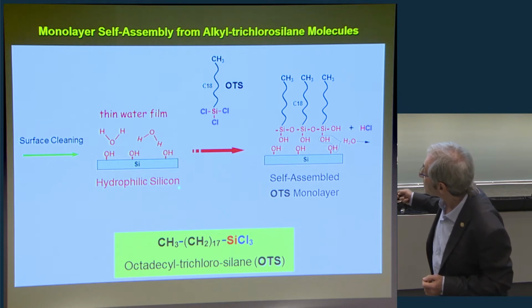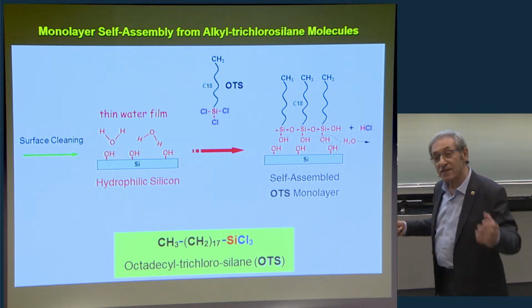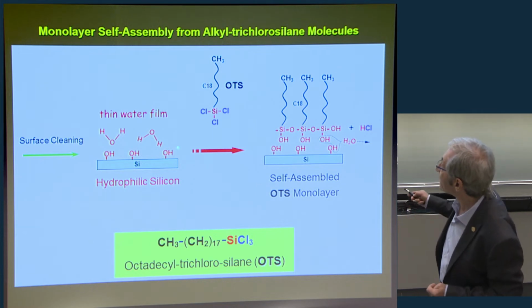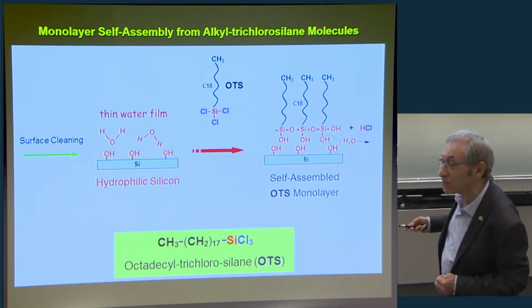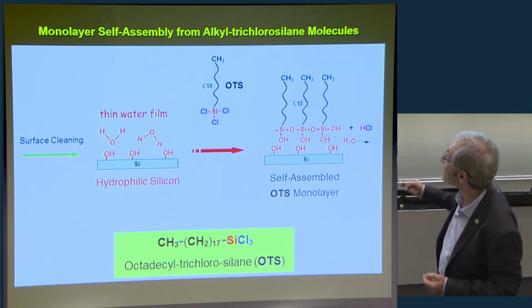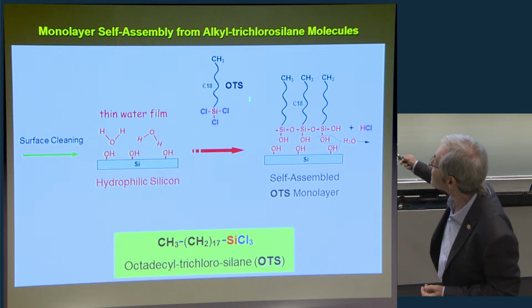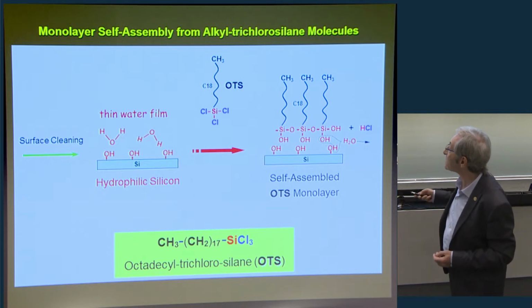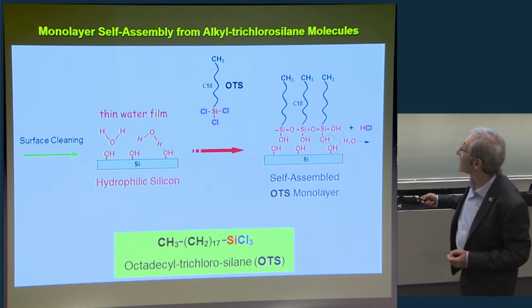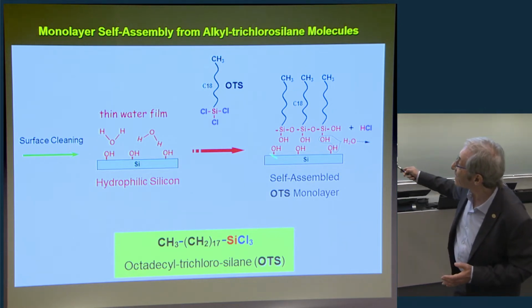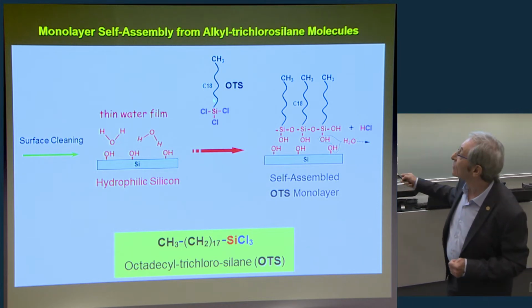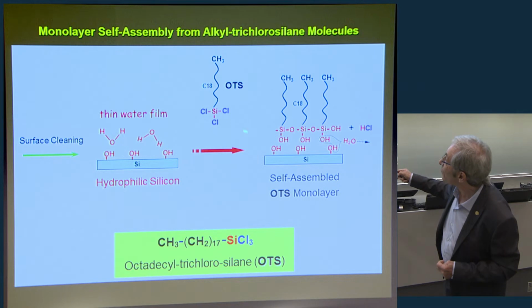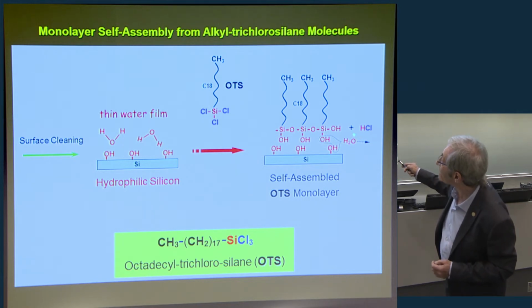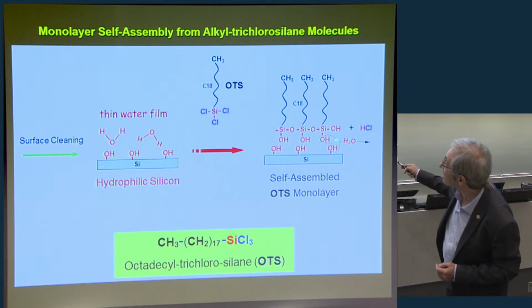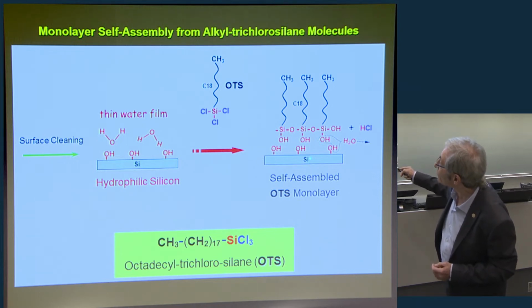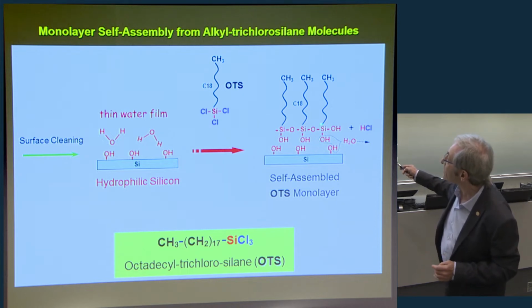And if the solid is clean, and this is another problem, how to clean it and to keep it clean, then you will always have a thin layer of water, which may be a monolayer or several monolayers of water on the surface. Then you bring it in contact with a dry solution of these octadecyltrichlorosilane molecules, and then the entire assembly and chemistry occurs at the surface. So the chlorines are removed, hydrochloric acid is released, the silanols can condense, and they may form bonds to the surface, covalent bonds and also lateral bonds.